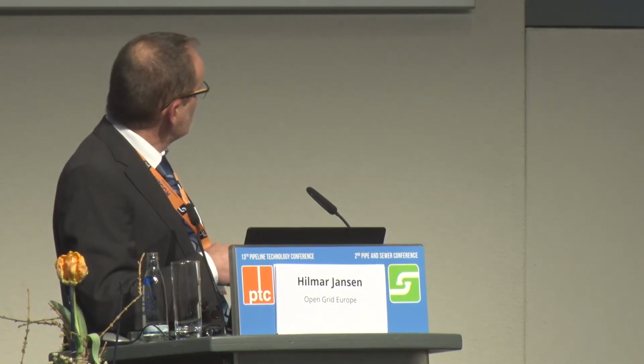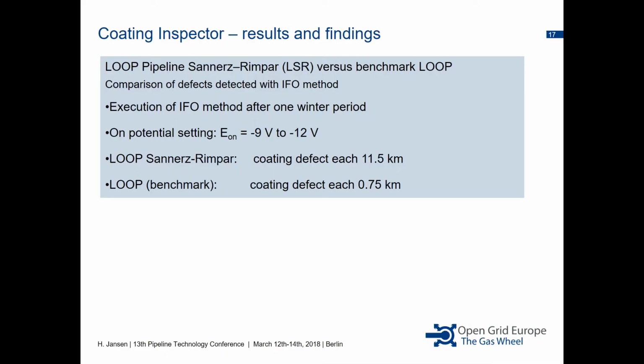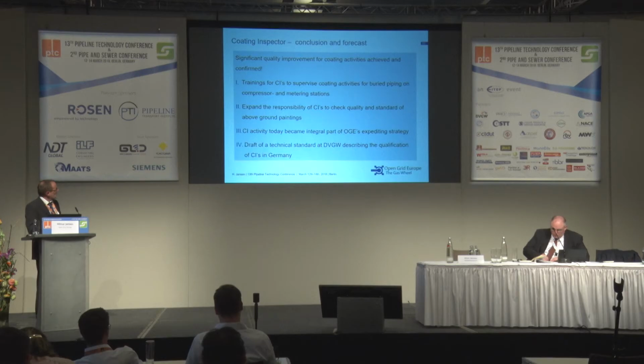And on the loop Sannerz-Rimpar, there was one defect each 11.5 kilometers, and only on the benchmark pipeline we had each 750 meters one coating defect. So these two key indicators, the average coating resistance and the measurements from the EITEP, made us sure that we had made the right decision to give quality control an extra coating inspector, and that we have done the right steps in order to increase the coating quality on site.